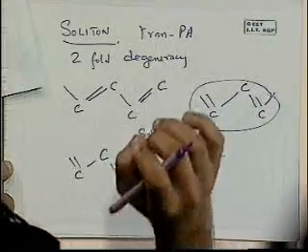And fundamentally, you may think of a soliton like some kind of a defect level in the band gap. If you think of polyacetylene having a band structure, there's a band gap. What the soliton formation does is to introduce like a shallow level in there. And so you can excite out of it and so on using semiconductor terminology and create conduction. Rather than exciting across the band gap, you're exciting from a shallow level, as if it's like an N-type defect. N-type dopant.